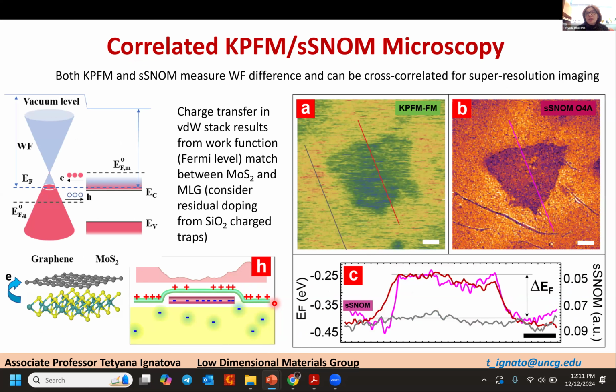Of course, we know that optical characterization is always limited by diffraction. To enhance resolution, we can correlate this data with scanning tip techniques like AFM or SNOM, and then create higher resolution for this optical characterization. For example, on this slide, we calculated charge transfer in van der Waals materials, graphene and MoS2, by applying KPFM and correlating KPFM and SNOM. This type of correlation procedure allows us to calculate exactly the amount of charge transfer in this heterostructure.